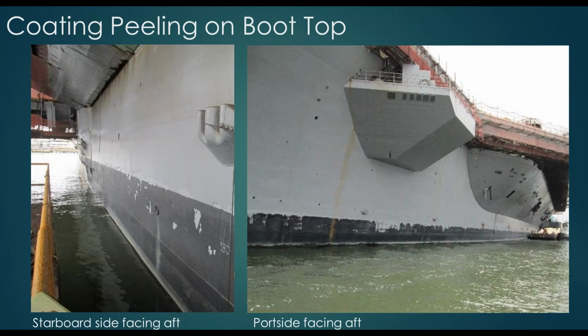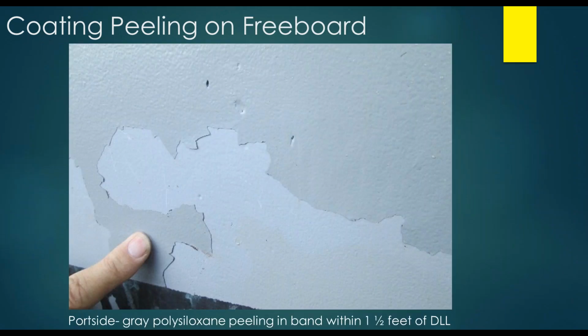The coating was observed to be peeling on the boot top, and this was occurring on both sides of the ship, primarily though on the port side. The images we see here are on both sides of the ship, looking towards the rear of the aircraft, or the aft. Similarly, peeling was also observed sporadically in the freeboard, within a band above the deep load line that extended maybe a foot to a foot and a half.